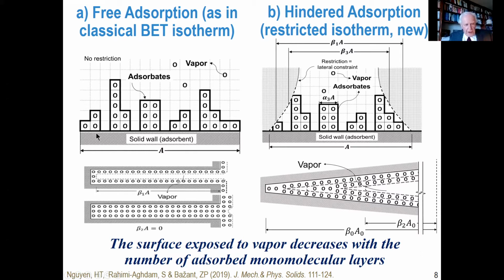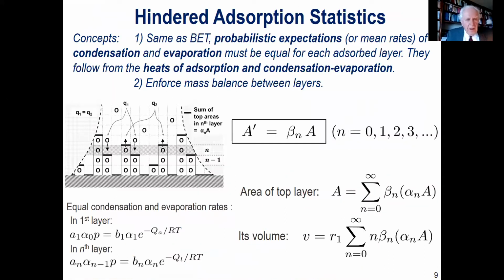Similarly, if you have cylindrical pores or slits, a pore which is 3 molecules wide allows some access of vapor and this contact. But at high humidity, it is filled, and suddenly it is not accessible to vapor. So that's a serious restriction which changes the statistics. So we proceed by generalizing the procedure used in deriving the classical BET isotherm.